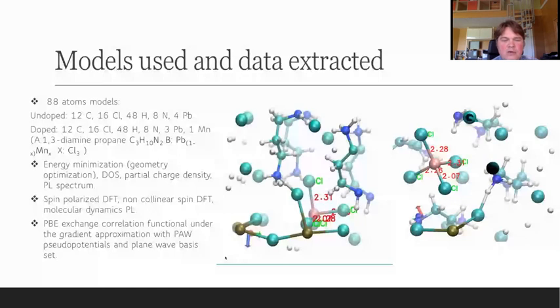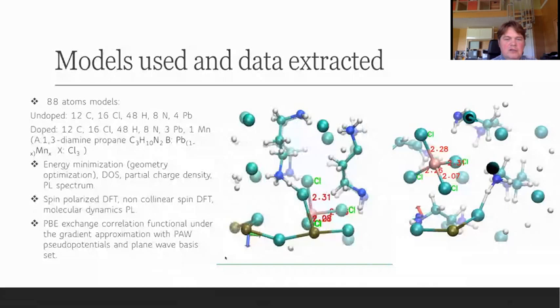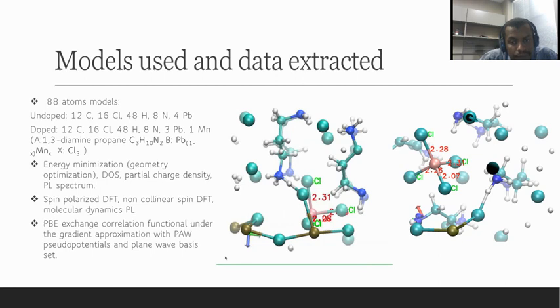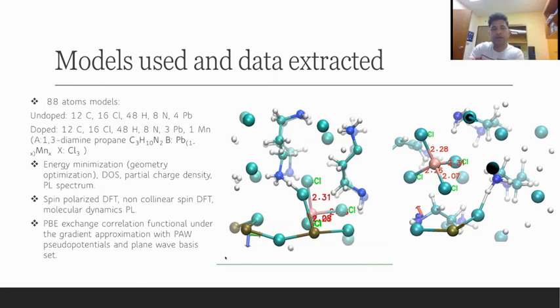And there was a search for a minimalistic model that shows as small as possible an amount of this lead halide layer, to focus more on the contribution of manganese. So to keep as many properties of intrinsic perovskite as possible, but to be as small as possible. And this model seems to be the right example. So this is not a mistake. It's intentionally simulated that way. Javad, please start your sentence over. So that means it's simulated intentionally as a 2D model to make a similarity with the experimental result. Is that right? Yes.